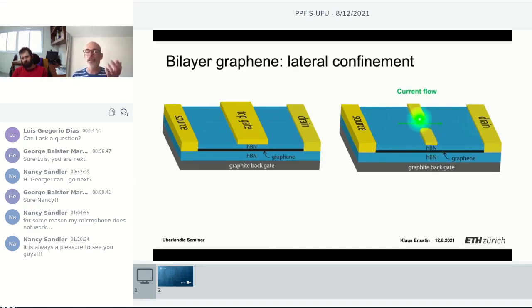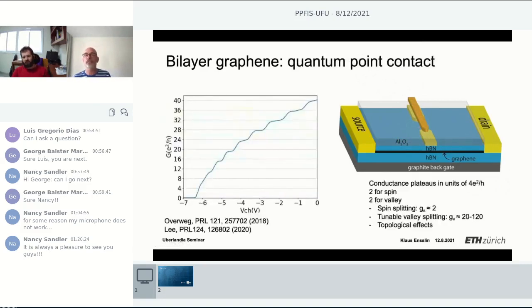Now here, this is not possible because if you make these gate electrodes more negative, at the same time you shift the Fermi energy in this little gap here and you make your barrier conducting. So this doesn't work. In order to have a band gap below the split gate and to have the Fermi energy in the band gap, you cannot touch this gate electrode here. So what you do is you cover it with another insulator and yet another gate on top of this little constriction so that you can locally tune the Fermi energy in this little constriction. And if you do that, you can measure the conductance as a function of this little gate here on the top. And you see, you can pinch off to zero conductance at very negative voltages. And then you see very nicely quantized conductance as it has been seen in gallium arsenide back in the 1990s.